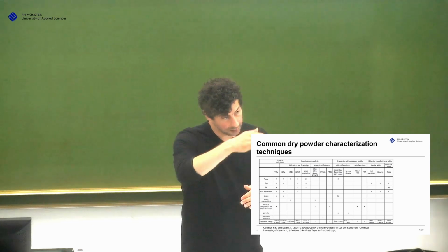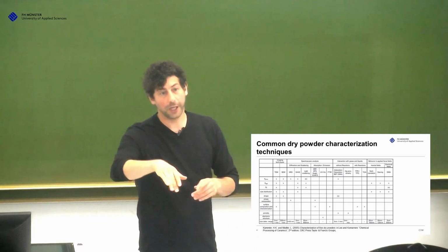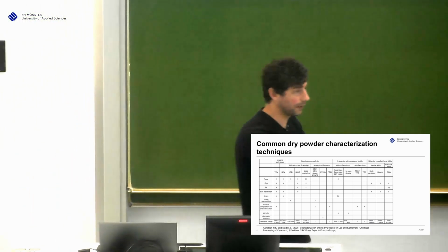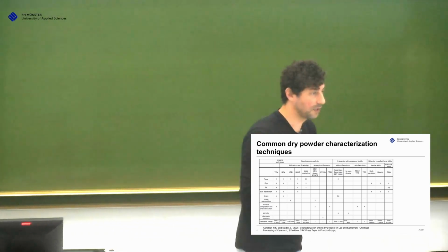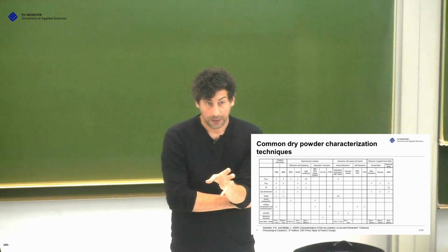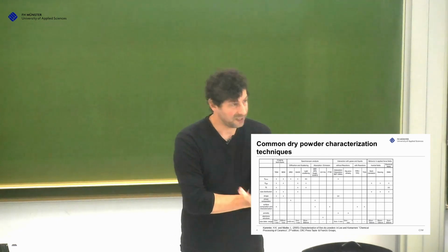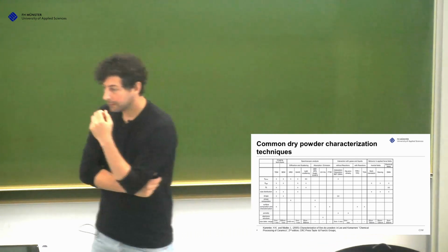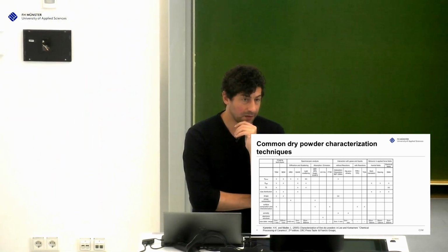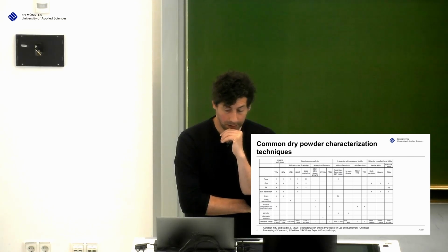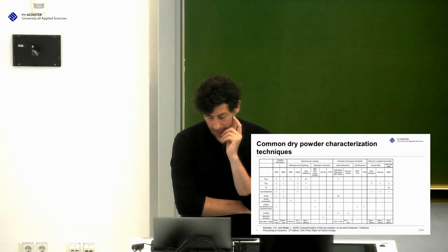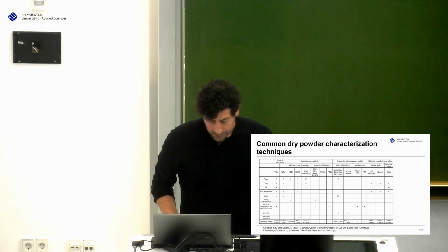So depending on the profile of the TGA, you can link the TGA result to, for example, the FTIR result or other surface characterizations. What you need to know is what is on your surface, and TGA tells you how it behaves. And then you also get the amount, because FTIR does not really tell you the amount of water. If you really want to know, okay, there is water, how much, then you would work with TGA.